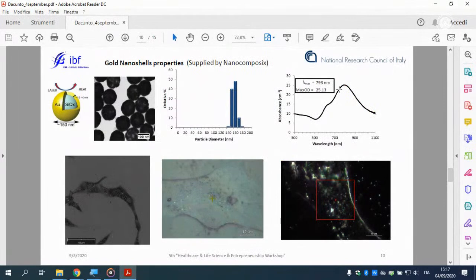Okay, what happens if we use SERS? We introduce gold nanoparticles, in particular gold nanoshells, in our cells, and see what we can observe inside the cell. We have nanoparticles with a diameter of 150 nanometers, with dimension less than 200 nanometers. The nanoparticles can be encapsulated inside the cell.